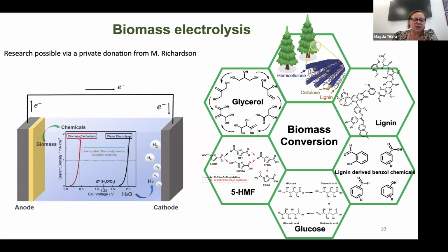And the nice thing is, if you look at biomass compared to water, you would see the potential at which these oxidation reactions happen is much lower. So overall, the bias that you need to put in this electrolyzer, the electricity, is much lower because of the low potential. So that would give you quite a lot of savings in the cost of the hydrogen you would be producing compared to the one from water electrolysis. And I forgot to say that that's a big problem, and that's why green hydrogen is not implemented today, because it's still very, very expensive compared to gray hydrogen. It is about 10 times more expensive. So we need to bring the cost down in order to be widely adopted in industry.